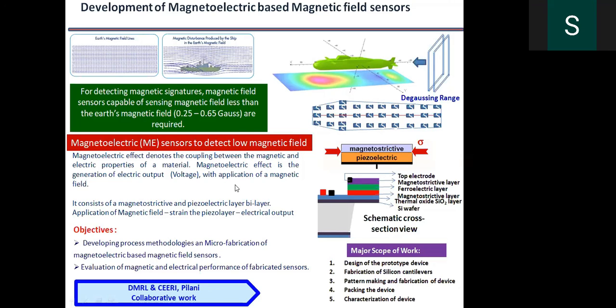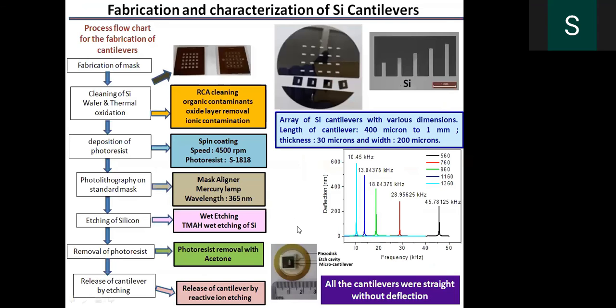So for this one, we have used a magnetoelectric material. As I told you, magnetoelectric is nothing but a magnetostrictive and piezoelectric material, which is a sandwich layer, and we have used a cantilever based magnetoelectric layer for fabricating this device. We have used a standard lithography process for developing these devices. We have used a photolithography technique for developing these cantilevers. All the silicon cantilevers were found to be straight without any deflection.